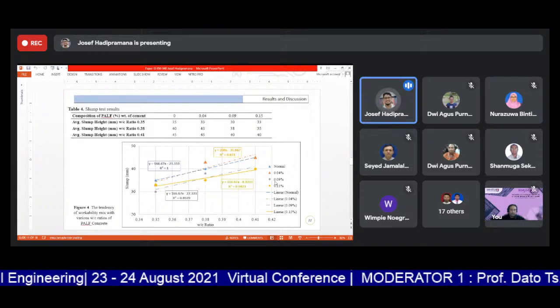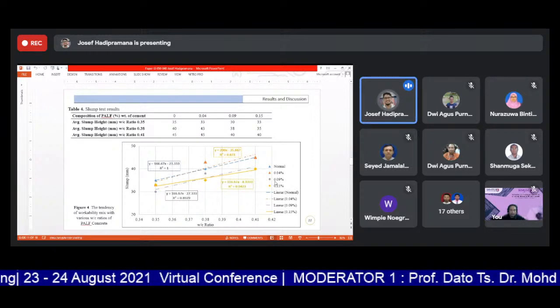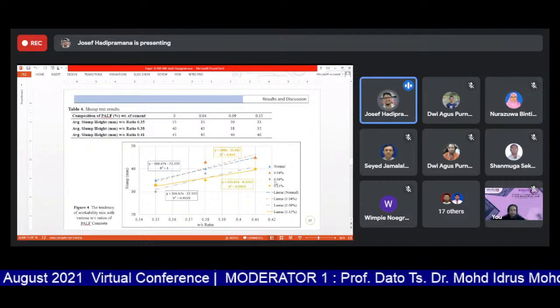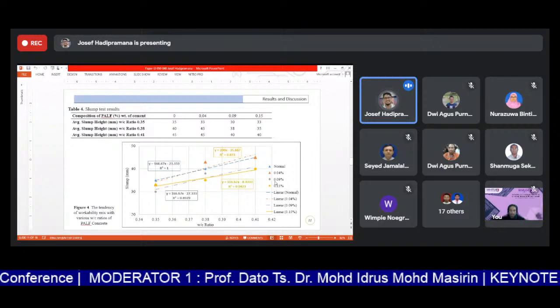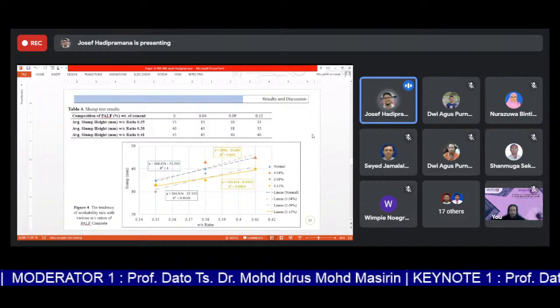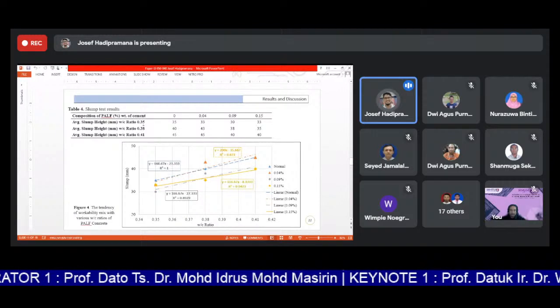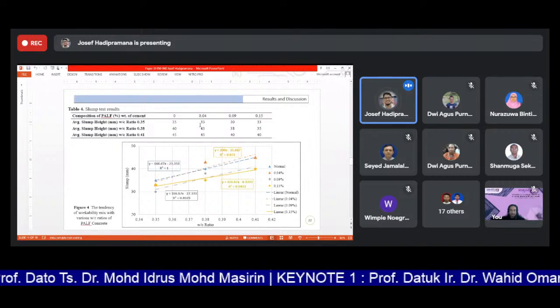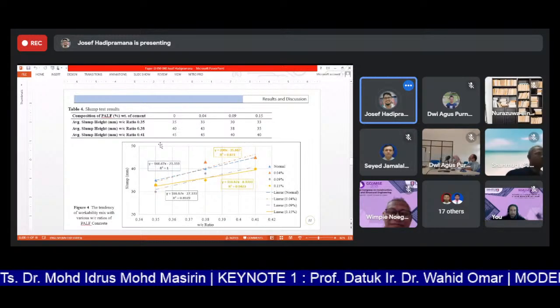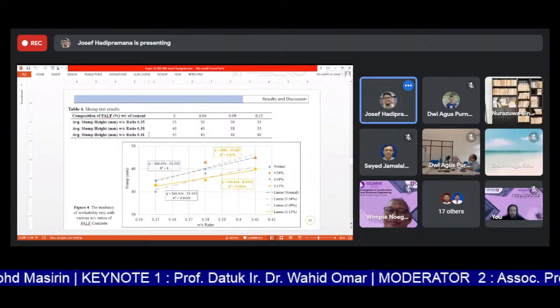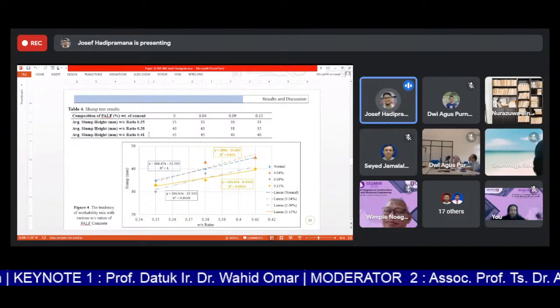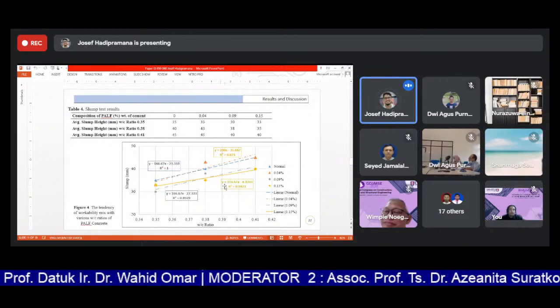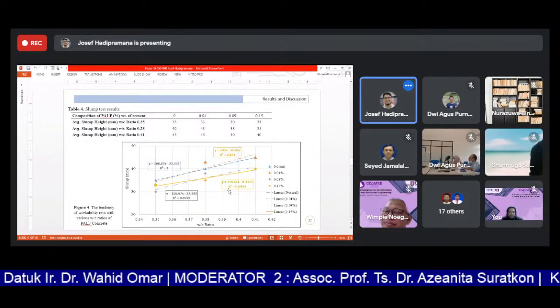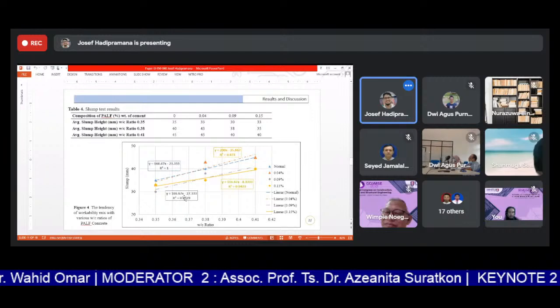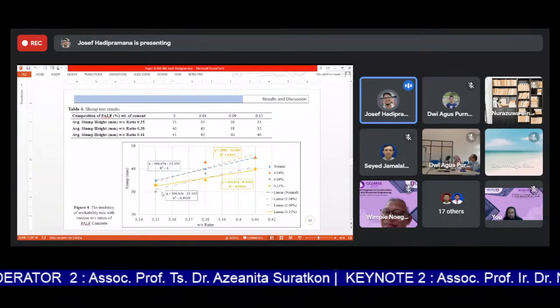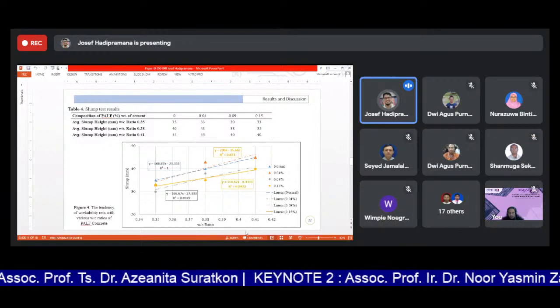The table shows the average height of the slump in all variations, where the lowest slump is with a water-cement ratio of 0.35 here. It is the lowest slump, and the highest one is 0.41. So that is the tendency of the relationship between slump and the water-cement ratio, it can be mapped with the water-cement ratio.